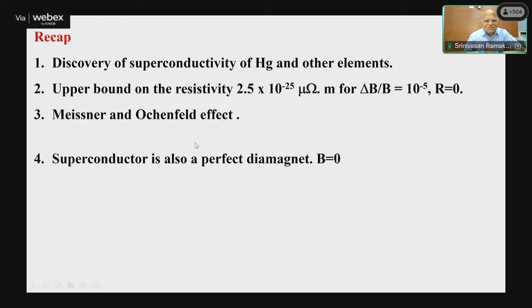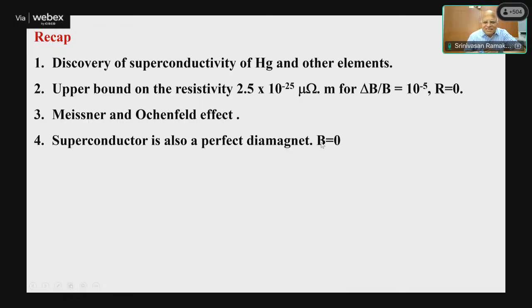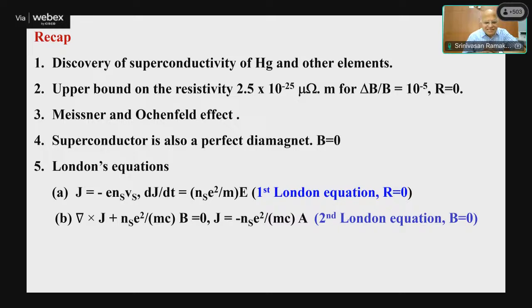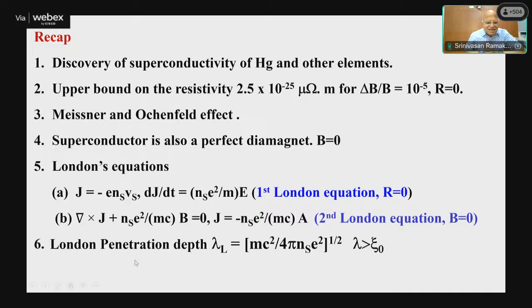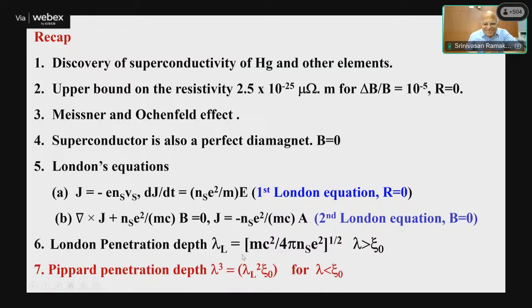Then we discussed the Meissner-Ochsenfeld effect, which showed that it is a perfect diamagnet. It is more than a simple fictitious material where the resistance is simply zero. So it's more than that. So you have London's equations. This is the first London equation, and this is the second London equation, which goes to the penetration depth. Then you have Pippard's coherence length, London's penetration depth, which is given by this expression, where lambda is greater than xi, and Pippard's penetration depth, where lambda is less than xi naught.